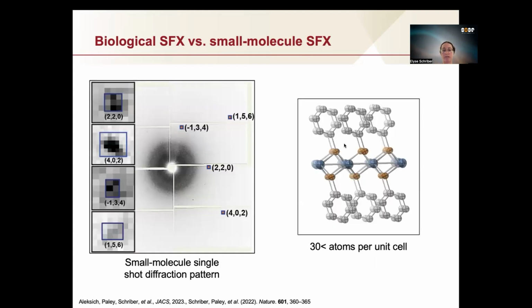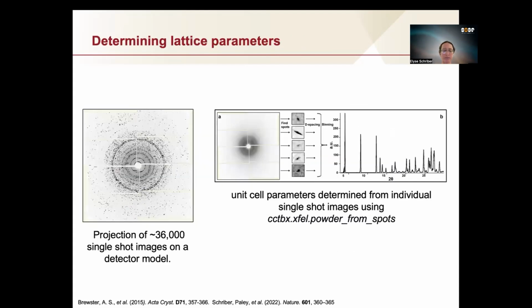In small molecule SFX, you maybe have 30 to 50 atoms per unit cell. And what ends up happening is you have far fewer reflections per shot, and no obvious form of periodicity. So the standard methods for indexing these single shot images fall apart when you have this very sparse pattern. You really can't identify any sort of real periodicity, and the method essentially falls apart at that point.